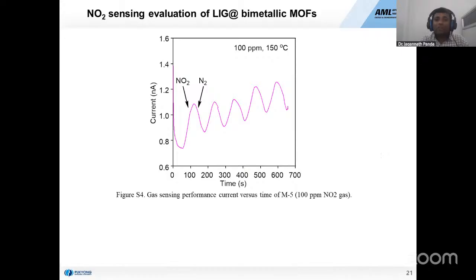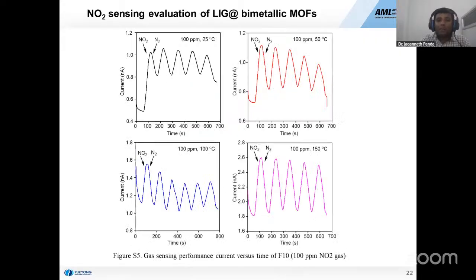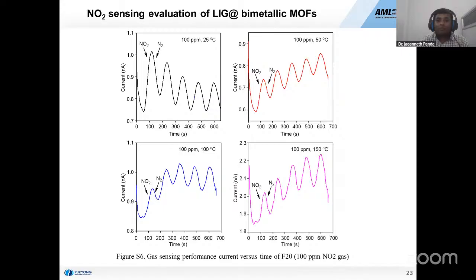Then we also performed it at high temperature, and at high temperature too it shows that the NO2 peak is larger compared to N2. Also, we varied the temperature as well as the samples. We got the best performance when the metal ion content is increasing. When more iron atoms are introduced, the sensitivity increases. Similarly, we performed this for different samples and different concentrations of NO2 gas flow.